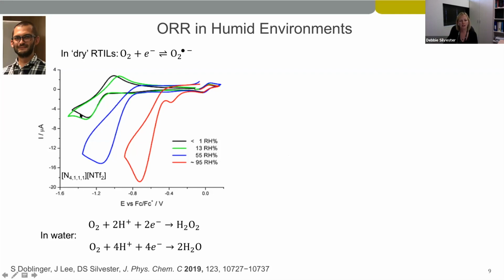The black line is the 1 electron reversible reduction of oxygen to superoxide. You can see nice reversible voltammetry. Then as you increase the relative humidity level, when we get to 13% humidity, the green line shows already a slight increase in the current and also a separation in the peaks. As you go to 55% humidity, the current increase is more than double and the potential changes. And as you go to a very saturated environment, 95% humidity, we have almost 4 times the current and a very shifted potential for the reduction.